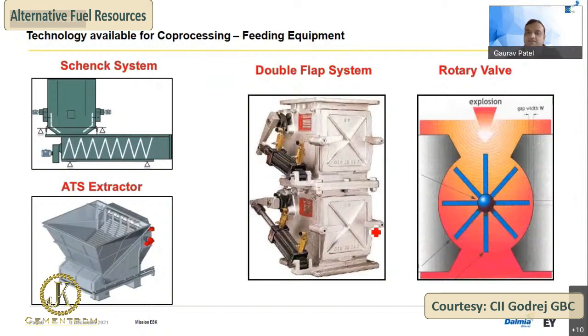But ATS double flaps are suitable for reaching 15 to 20% TSR. Beyond that, we should go for rotary air locks to avoid batch feeding of the material into the calciner. Once we increase the TSR, tonnages will increase, and these flaps will then work as a batch operation and feed the material in a batch process.